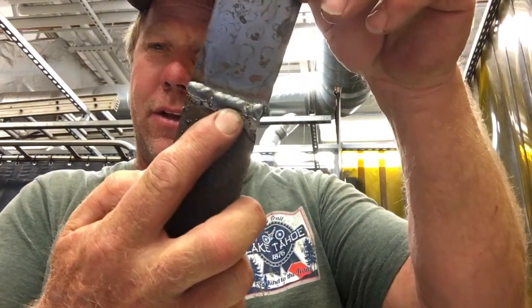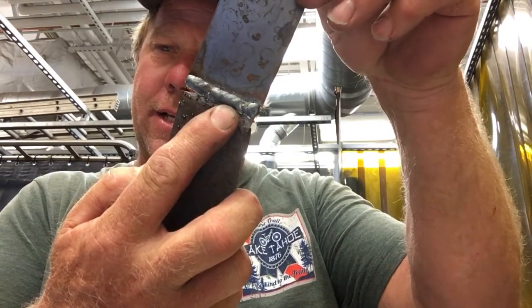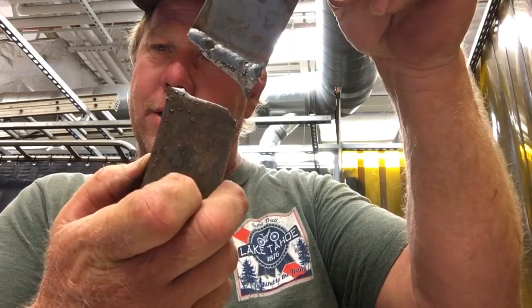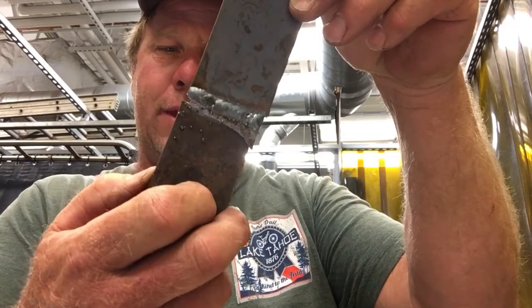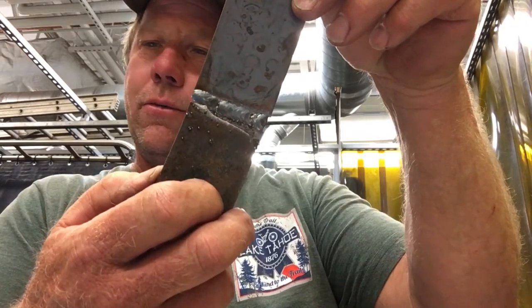This one probably could have held on a little bit longer, but it propagated that tear, and then that tear just went across. Bang. That's why you got this funny little rip off. But that tear is at the toe of the weld. That's where you're always going to see a heat affected zone failure. Remember, heat affected zones, not the weld, not the original material. It is the material that is affected by the heat.